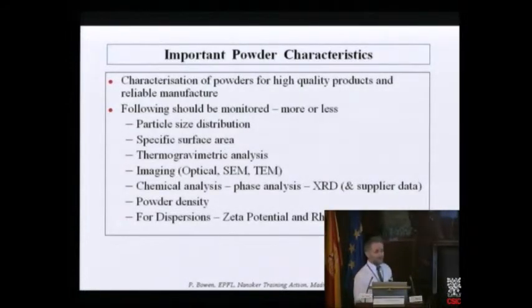Okay, so for characterizing powders, I'm going to put up a little list of the things that I think are really important. Particle size distribution, specific surface area, thermogravimetric analysis, imaging. If you don't have an image of your powder, any particle size measurement which assumes the particle is spherical is inherently wrong. So you have to have an idea of how close to spherical your particle is. Chemical analysis normally comes with the supplier's data. If not, even phase analysis, X-ray diffraction can be important.